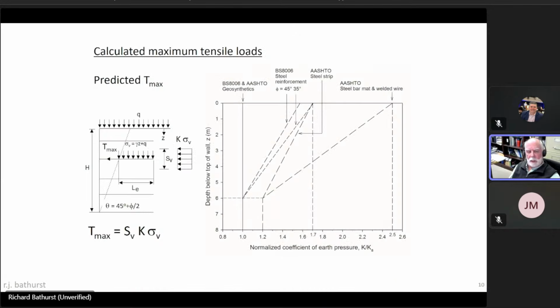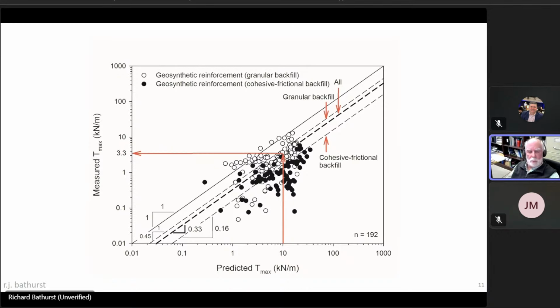And how this was done was that for each instrumented layer in these walls, and all walls, we simply went to the existing design methods at that time and predicted what the maximum load in that reinforcement should be according to theory or the design methods. And this is the simplified AASHTO method, if you like. And so here we have in hand the predicted maximum load, and we then compared that to the measured value.